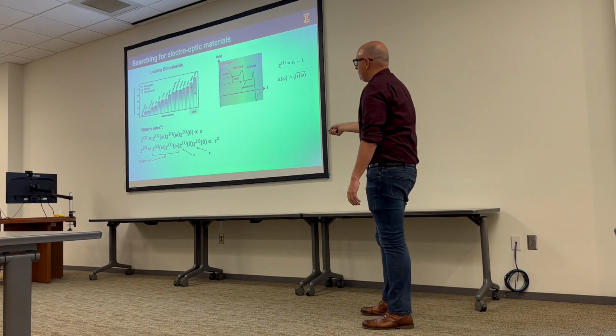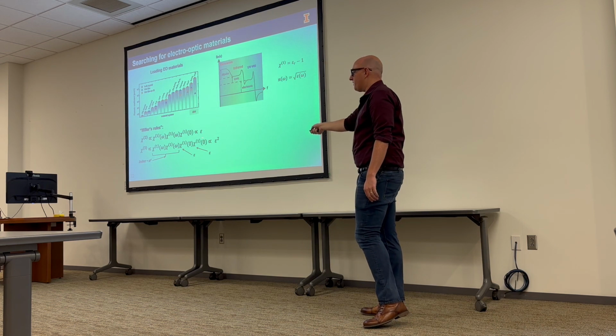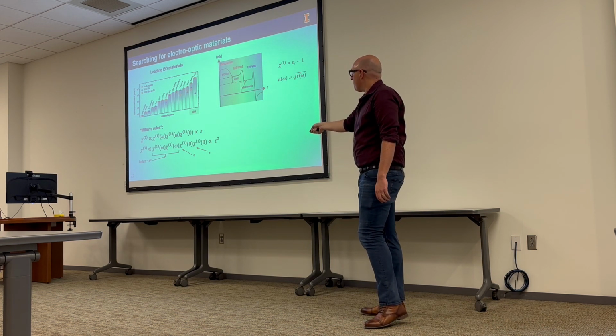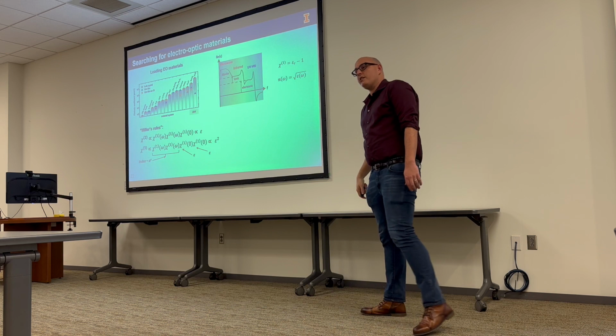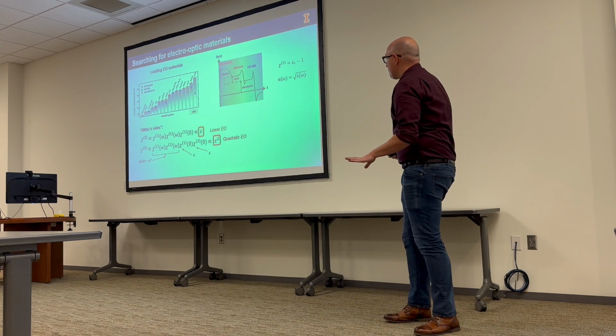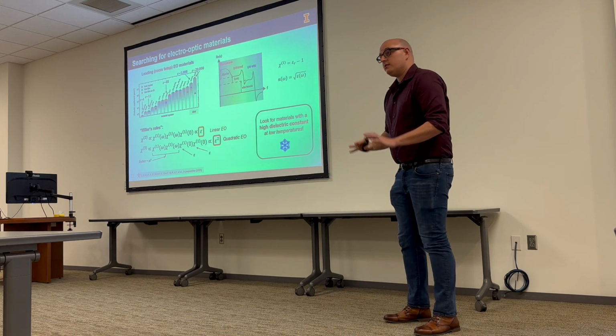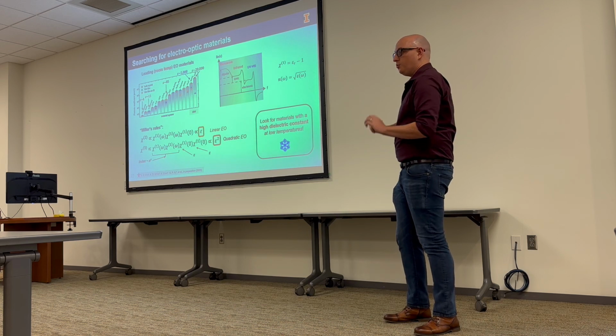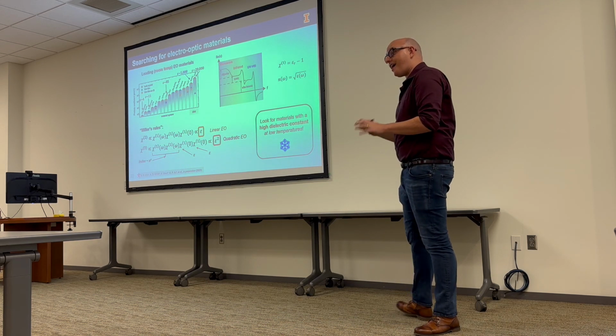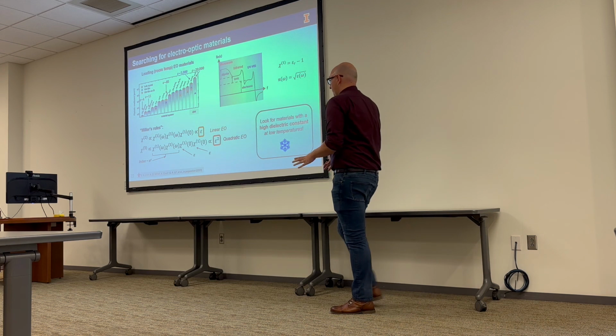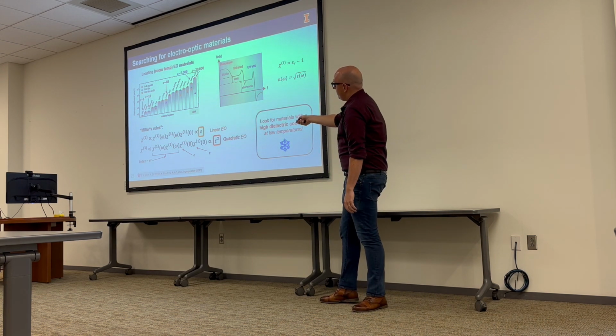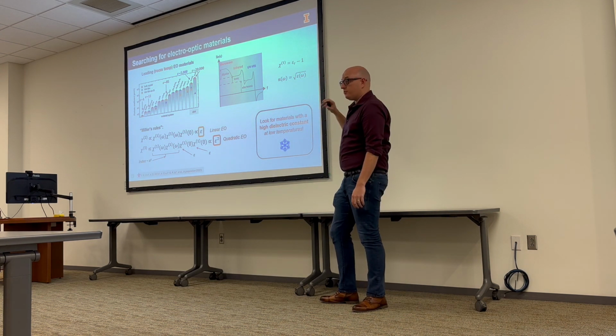If I want Chi-2, I want this thing big because I get a linear term with it. If I want Chi-3, I want this thing big because I actually get it squared. So the moral of the story here is, if I want nonlinear optical materials, what this tells us is I just want materials that have high DC dielectric constants. And that's great, and it completely explains this entire trend, which is awesome.